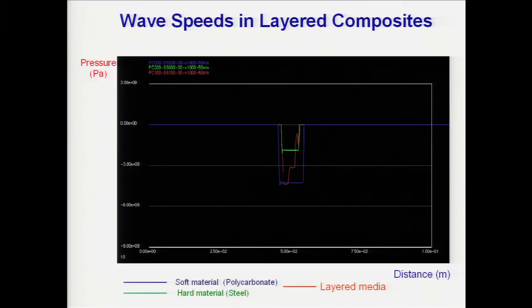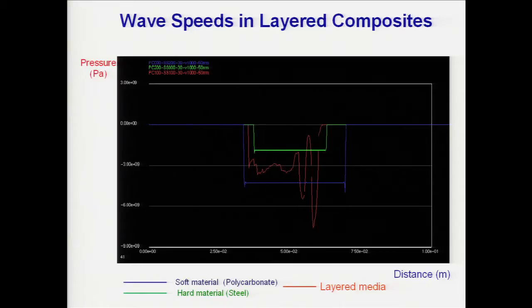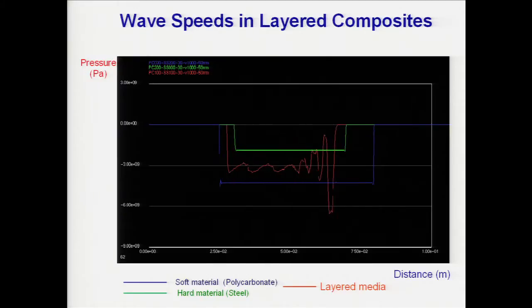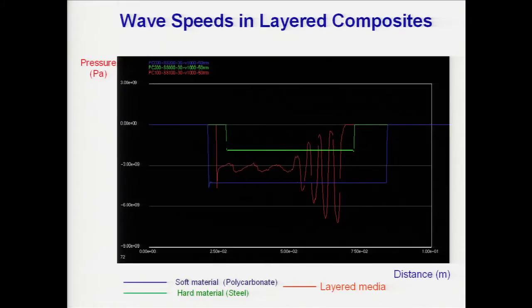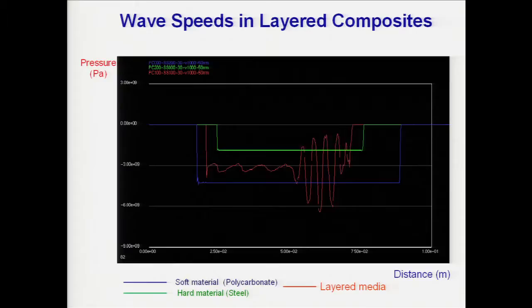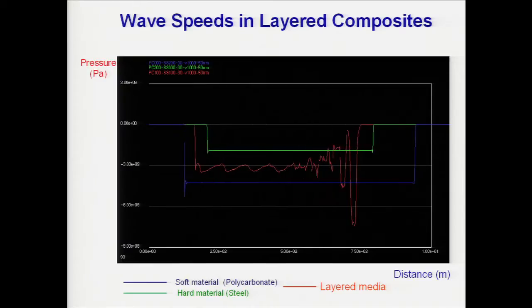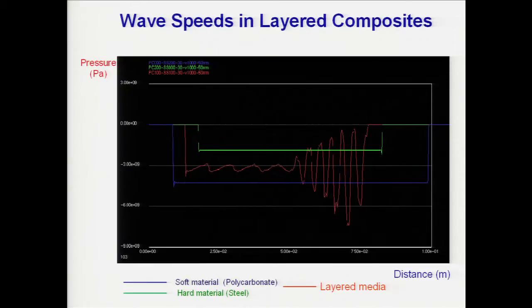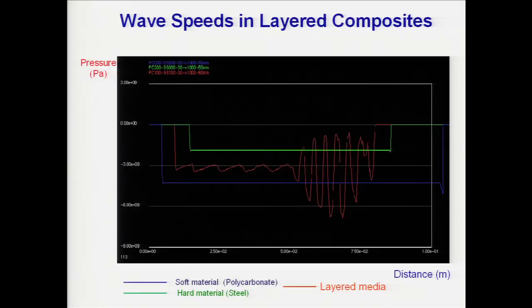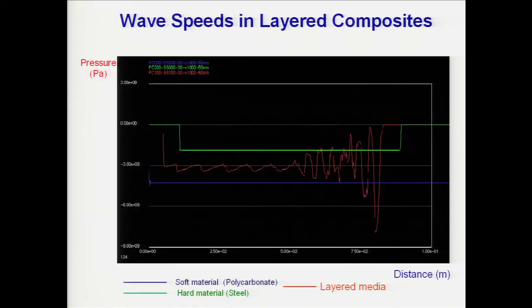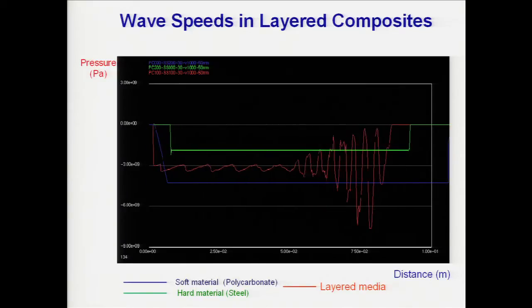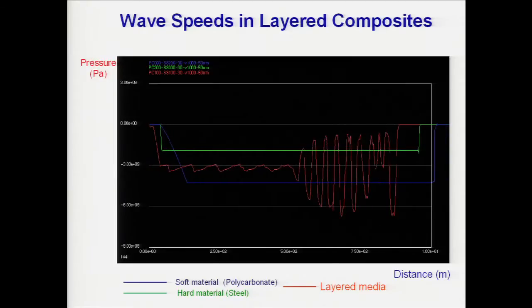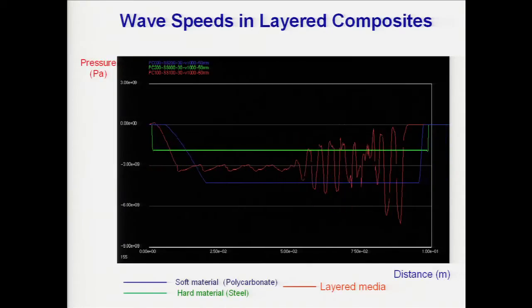So now, this movie shows when you impact this target. Here, there are three things running together. This is the hard material which is being impacted, a homogeneous hard material. This green is the soft material which is being impacted. These are the shocks which are propagating. This shock wave speed is higher. This wave speed is slower than the hard material. But you can see the composite or the layered media is propagating slower than either of the two speeds.